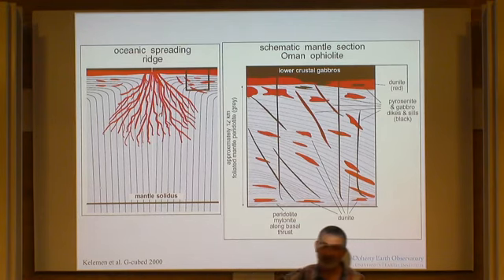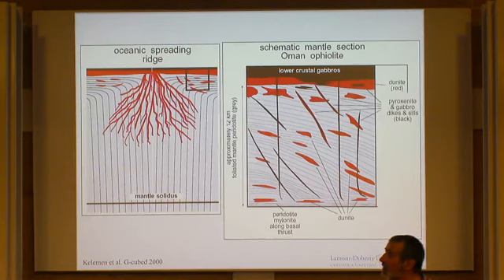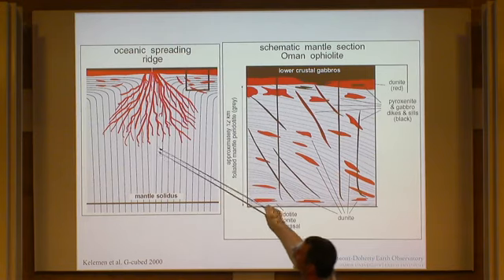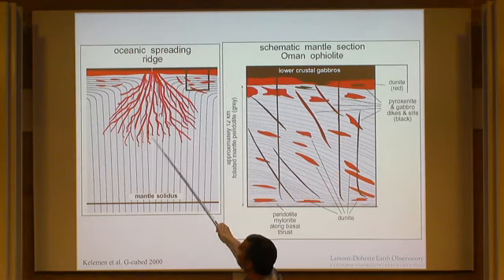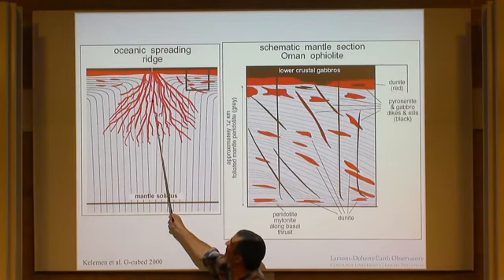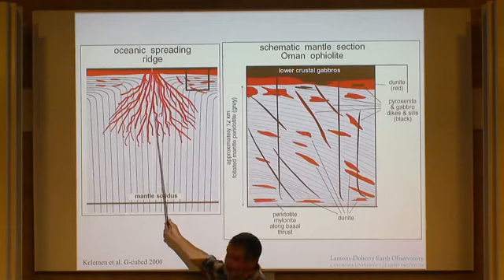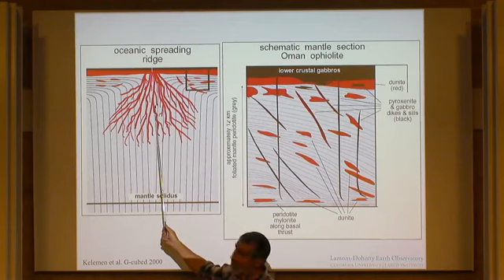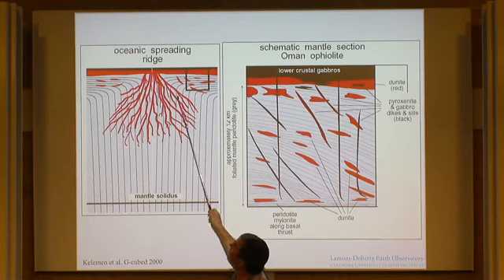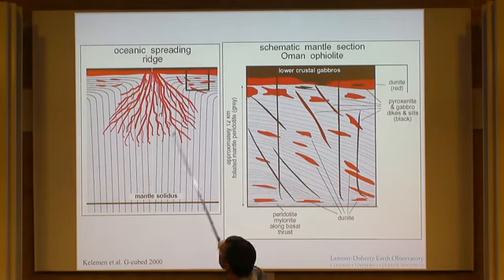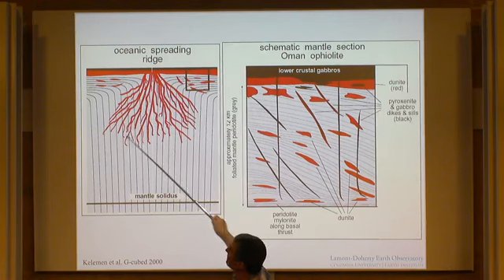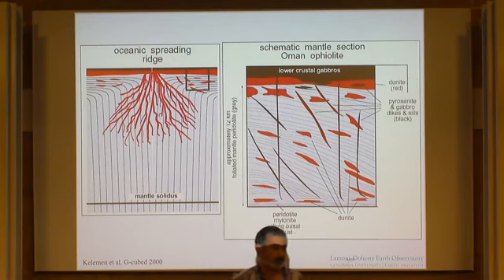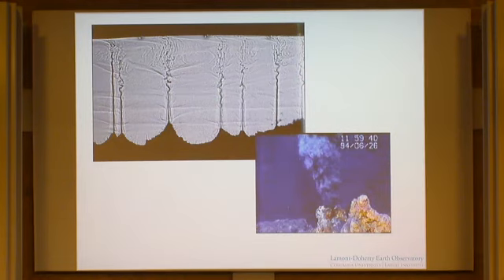But anyway, maybe these observations at this kind of scale plus the models can inform something that looks like this. Coalescing network of dissolution channels that forms at about 45 kilometers depth and carries melt through it, avoiding equilibrium with the surrounding peridotite, which is still undergoing partial melting, and feeding these channels as it goes up, but allowing the crust to preserve some average pressure of equilibration with the mantle that's down here. And now maybe I will talk about this picture. I wonder if I can make this movie.